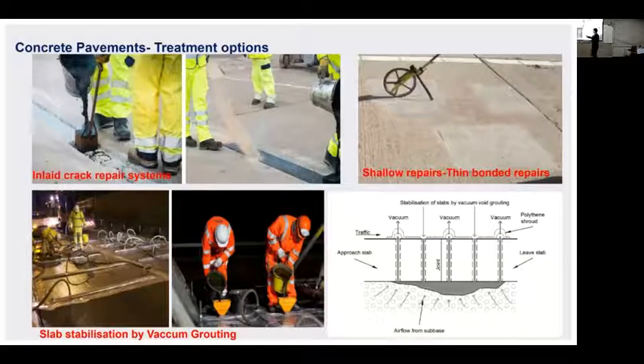The one on the bottom corner is for slab stabilization by vacuum and grout. This is mainly for scenarios where you have slab settlements, where you found out that you have a potential void under your slab. This is a technique that can be used to stabilize the slab. Literally you can force the air out to create a vacuum, and then they use either a resin-based or cementitious mortar to stabilize the slab. So that's one of the advanced techniques we still use.